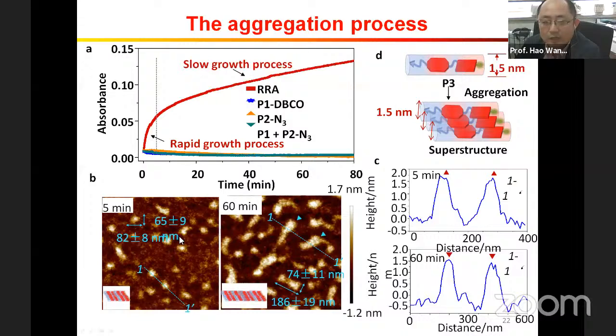We also used AFM to monitor the morphology of this molecule. At 5 minutes, we see very small dots, roughly 65 to 85 nanometers in size. But as time goes by, the aggregate grows bigger, like this one, where the width is roughly 74 and the length roughly 200 nanometers.